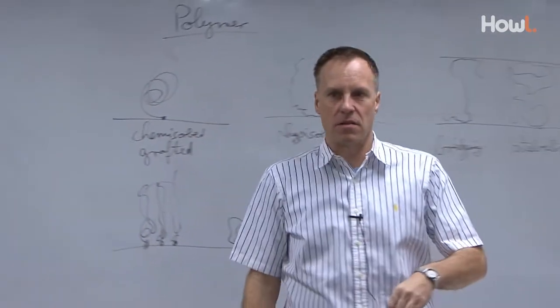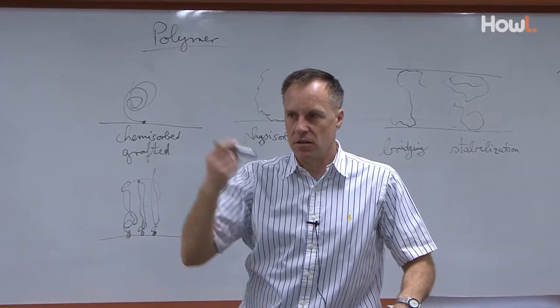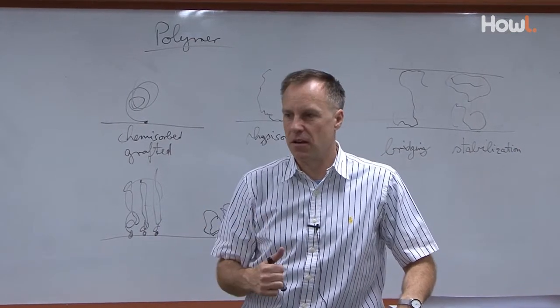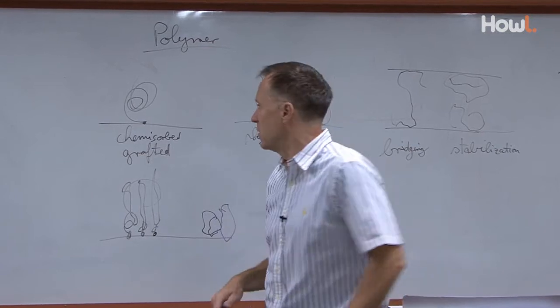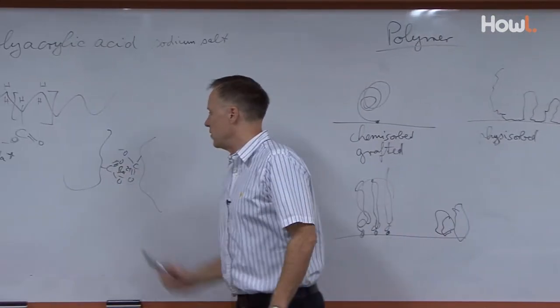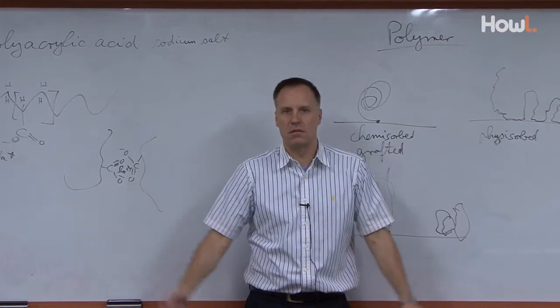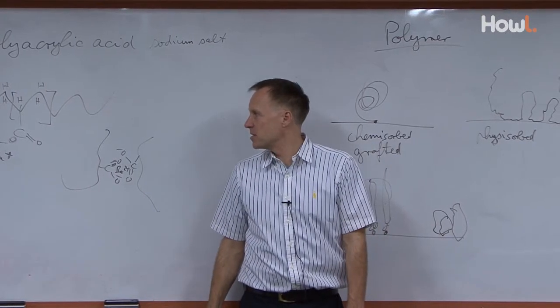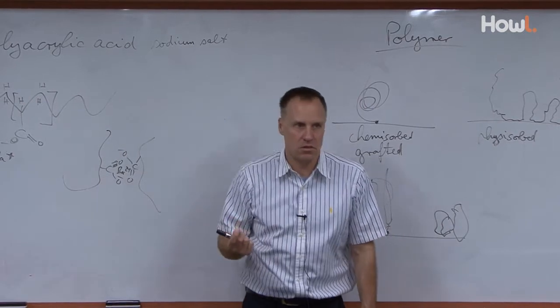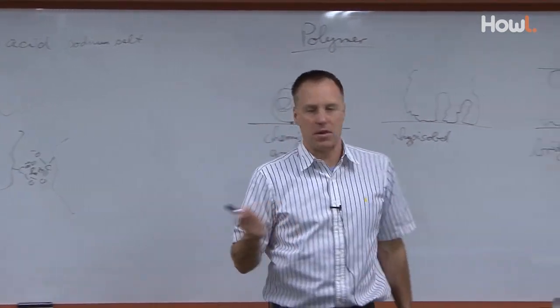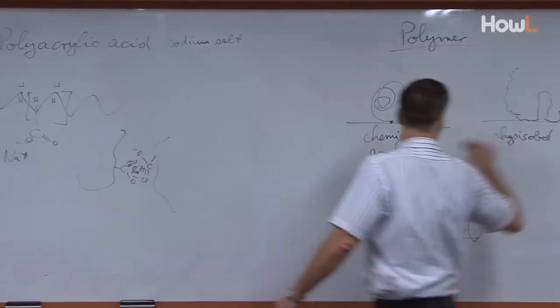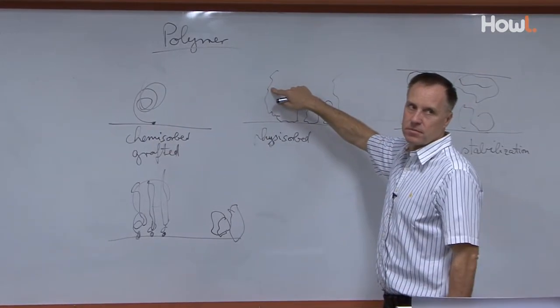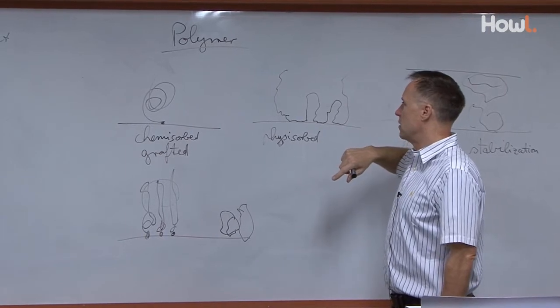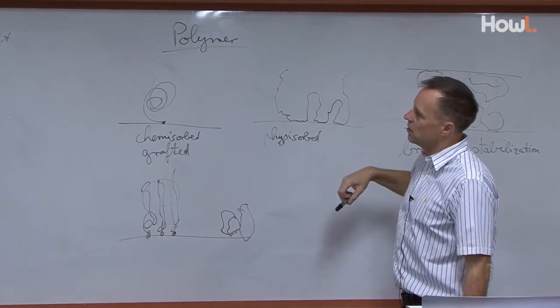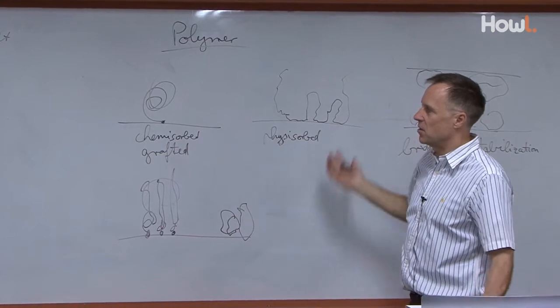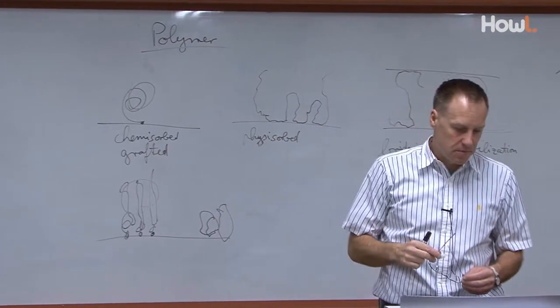And that causes the system to behave differently. Typically, you increase the viscosity, or you can even precipitate the polyacrylic acid if you have enough barium ions present. So polyacrylic acid works for dispersion, but it's not a really good dispersion because the chains that are supposed to stabilize here can interact with barium, and you do not do anything to hinder barium leaching out and so on. Yeah? So what else can we do then?